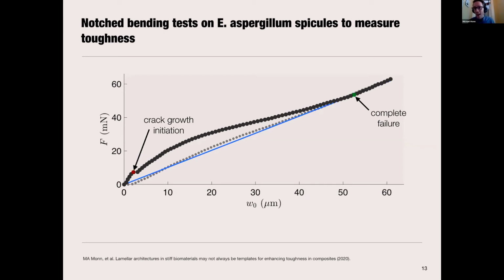For a particular specimen, after the crack has grown all the way through the cross-section and completely cleaved the sample in 2, there isn't a total loss of stiffness. You actually end up with a configuration that looks like this. So you have 2 cantilevers that are being displaced. So that should lead, at least initially, for small deflections, to a linear force displacement response, which is what you see after that point of complete failure. So that nonlinear region between the crack growth initiation and the complete failure, we believe corresponds to the region in which the crack is growing across the spicule's cross-section.